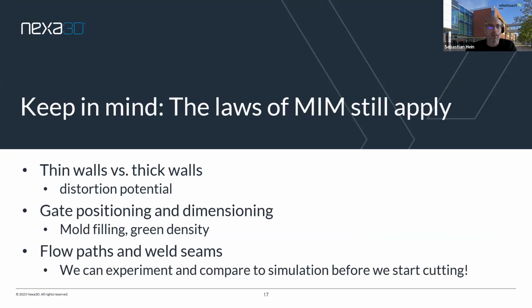Yeah. So as I said very early on, the laws of MIM, so to say, they still apply. So what's not good for a part for MIM, because you have to sinter it, are transitions from very thin to very thick walls, because this is always where you have the highest potential of distortion during sintering due to some bending, some forces that will distort the whole part. Gate positioning and also the dimensioning of the gate is important, because you want to be able to fill the mold properly. And of course, if the gate is too narrow, you lose a lot of pressure. You cannot really inject the material with a high speed. Or when you position the mold in a stupid way, let's say, you may get injection fronts that combine at a certain place where you get some cold weld lines.